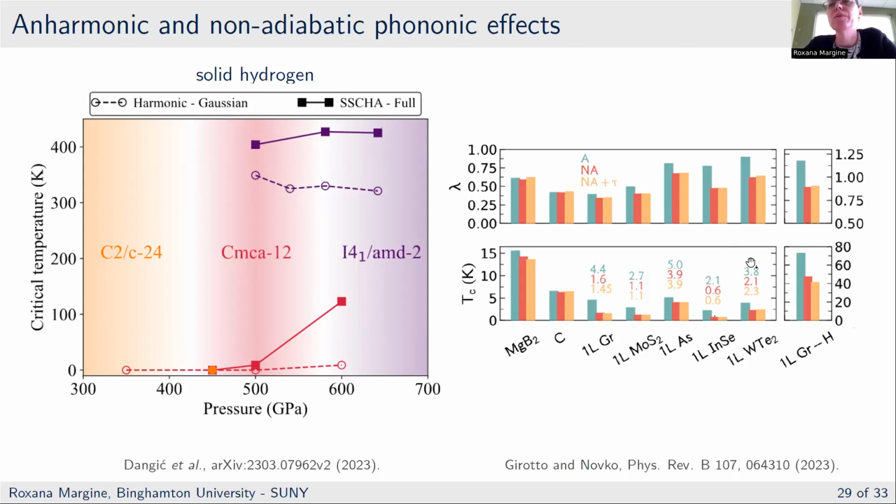Also, as I said, non-adiabatic effects can also affect the electron phonon coupling. So this study has shown that for some phonon-mediated superconductors, the lambda can be drastically reduced when the non-adiabatic effects are considered, and as a result, the critical temperature.